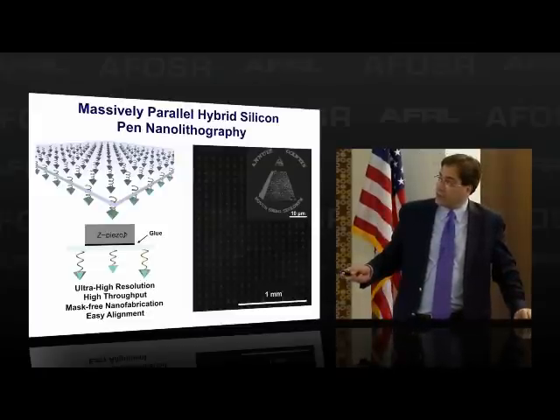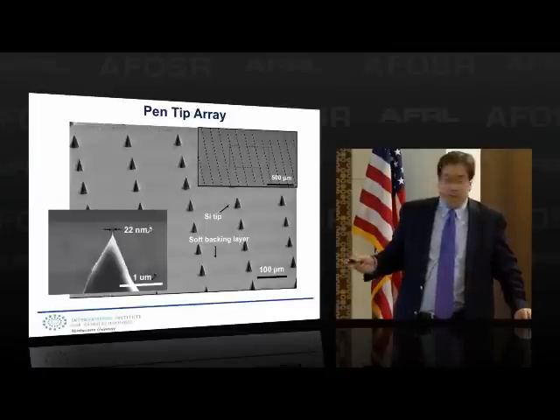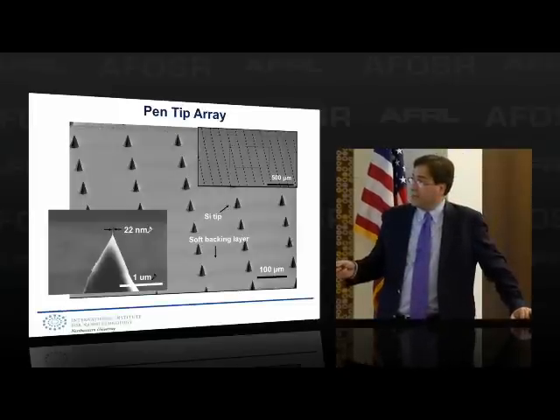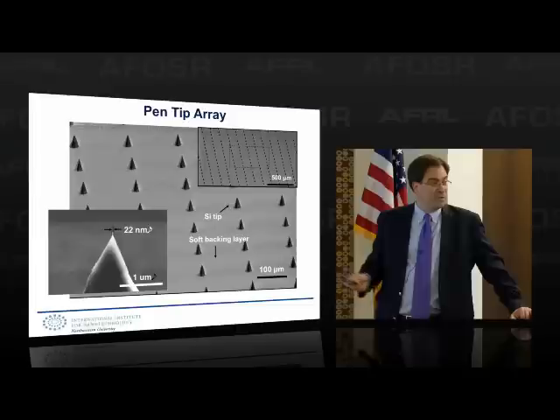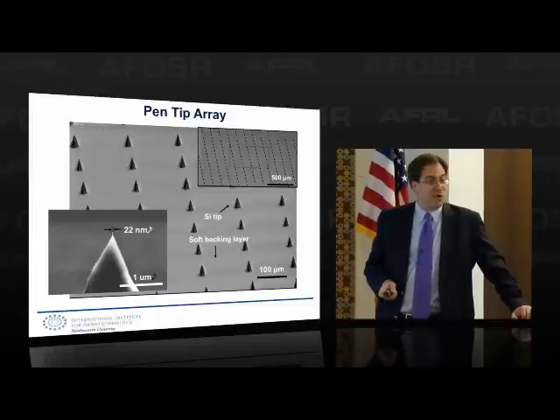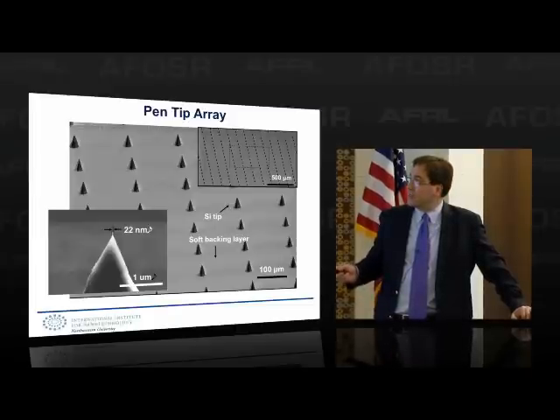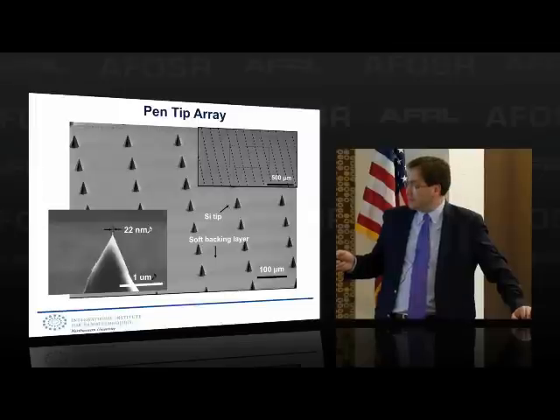Well, you could fabricate silicon or silicon nitride tips on an elastomeric pad with a transparent backing. Here you can see you can do that. These are really kind of interesting. If you look at this, it looks completely transparent. Most of this is polymer. These are silicon nitride tips. You can see the uniformity is pretty remarkable here, and this is the big advantage.